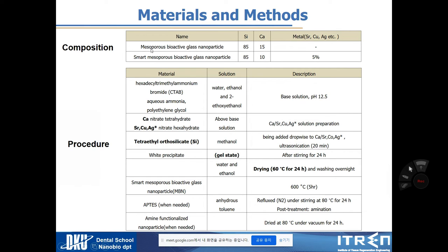Basically, the normal mesoporous bioactive glass nanoparticle has 85% silicate and 15% calcium. I want to additionally add certain elements which can show additional bioactivity. So instead of 5% calcium, I add strontium, copper, or silver at 5%. This is the methodology for making the nanoparticle. Basically, we start from a base solution at pH 12.5, and after a certain time the pH decreases, and the solution becomes nanoparticles as a gel. When we dry it, we can fabricate a bunch of nanoparticles with a size of more or less 100 nanometers.